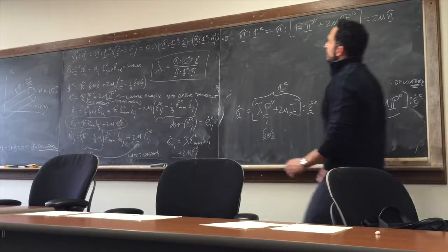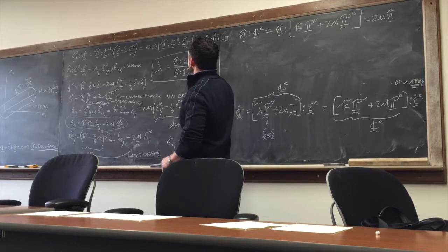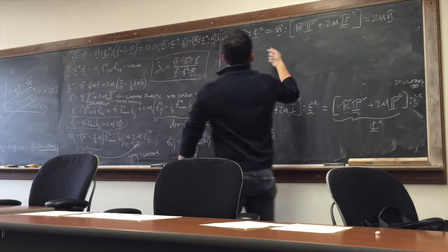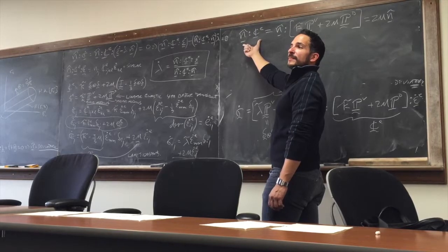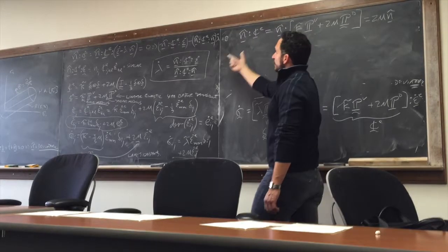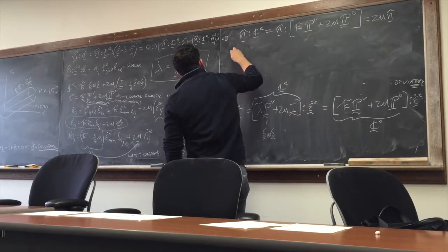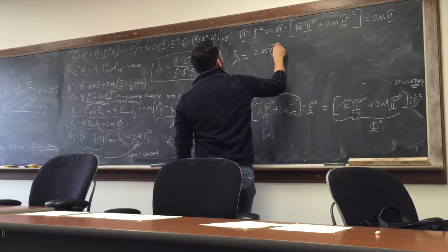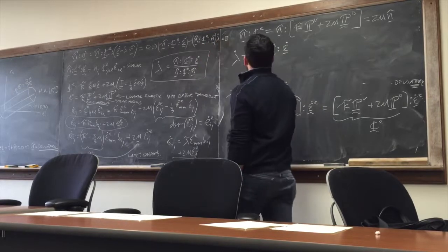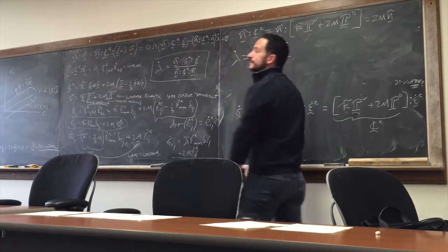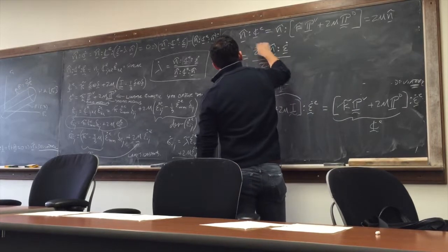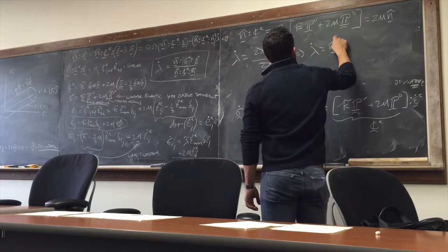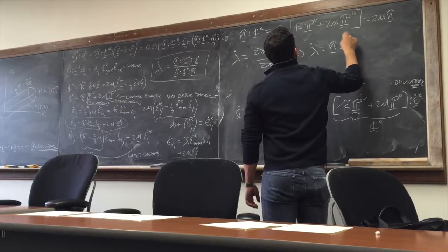All right, so my entire numerator has been resolved. What is my denominator? Given this result, 2 mu, right? So lambda dot equals 2 mu N hat double contracted with epsilon dot, all of that over 2 mu. The 2 mu and 2 mu go away, and lambda dot equals N hat double contracted with epsilon dot.